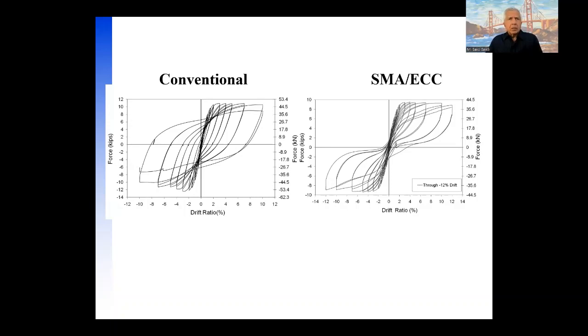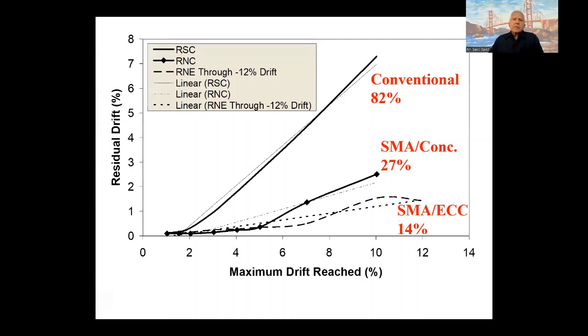So a well-designed conventional column exhibits the picture that you see on the left side. This is what we measured in our column test. And the one on the right is the one that has ECC and shape memory alloy. Again, a great deal of energy dissipation, but that flag shape response of shape memory alloy that I mentioned is maintained. Now, if we look at the residual drift, remember one of the damage types that we try to control was residual drift. So if I show residual drift on the vertical axis and the maximum drift on the horizontal axis, a conventional column exhibits very high residual drift.